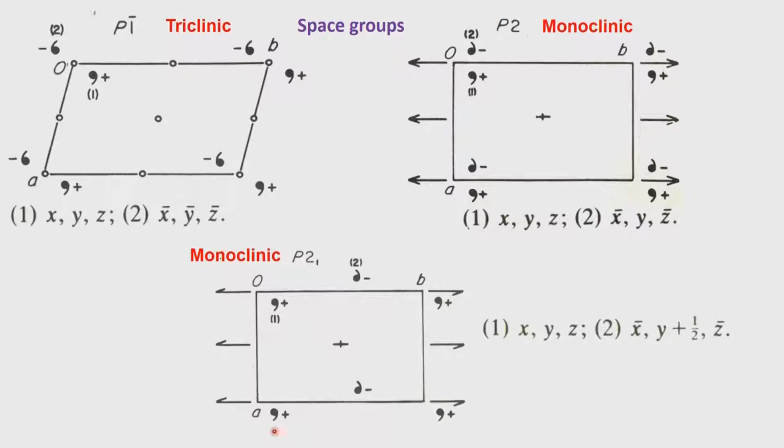So, these are the three simplest of the space groups we can discuss with respect to the equivalent points, with respect to special positions, and with respect to the generation of the equivalent points, and Z is equal to 2. If there is an object which has a two-fold symmetry, then Z will be equal to 1. If there is an object which is in P2-1, then there will not be any special position, because the translation associated will destroy the possibility of having a special position.